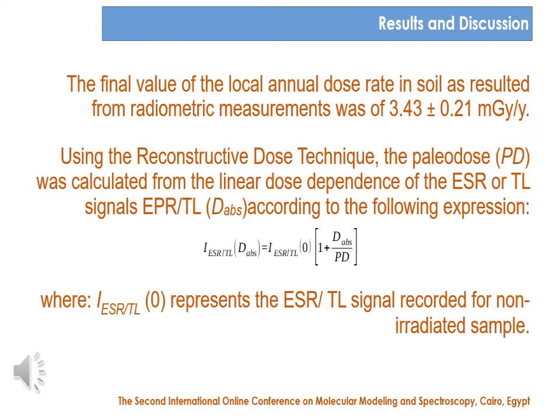The final value of local annual dose rate in soil, as radiometrically determined, was 3.43 ± 0.21 milligray per year. Using the reconstructive dose technique, the paleodose was calculated from a linear dose dependency of the EPR or thermoluminescence signals according to the following equation. It's a simple linear equation where the first term represents how the amplitude of both EPR and thermoluminescence signals increases with the dose.